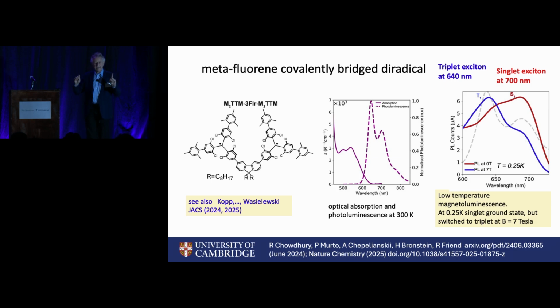So what we've got is a tiny difference in energy in the ground state between whether the 2 spins are parallel or antiparallel. Down at about a Kelvin is the exchange energy for this system. But that completely controls a color shift of about 300 meV or 250 meV. It's a huge color shift because it simply acts as a gate. If the 2 spins were triplet, it can't do that and form the lower energy 700 nanometer emitting band. So that's what you want for a spin-optical interface.